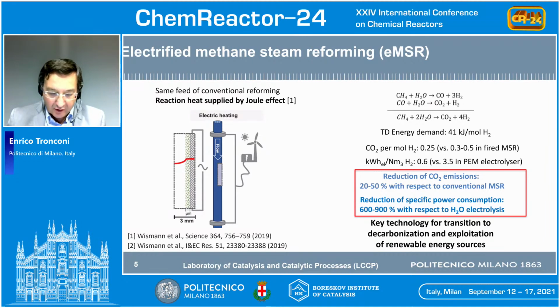Also, by removing the firebox, we substantially reduce the footprint of the reformer plant. Moreover, by bringing the heat supply very close to the catalytic site, we reduce the heat transfer limitations, which are the bottleneck of the conventional steam reforming process, paving the way to process intensification for the development, for example, of compact reformer units. Finally, this technology is also easy to integrate in existing process layouts, grants flexibility, and very interestingly, also fast dynamics. And last but not least, the specific power consumption per normal cubic meter of hydrogen produced is remarkably less than in electrolyzers.